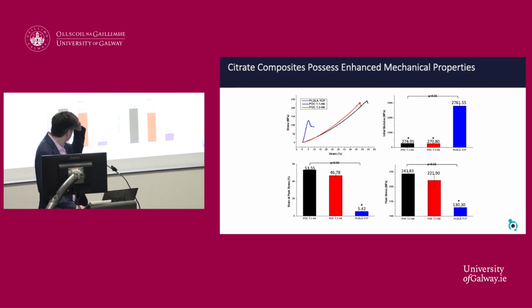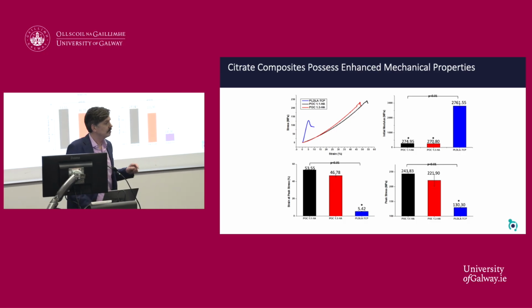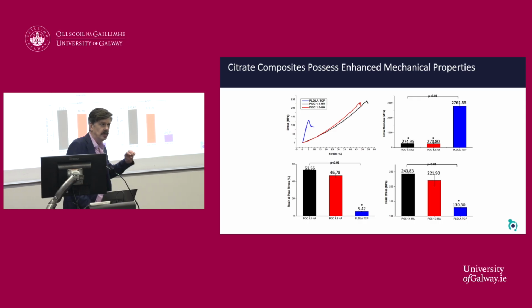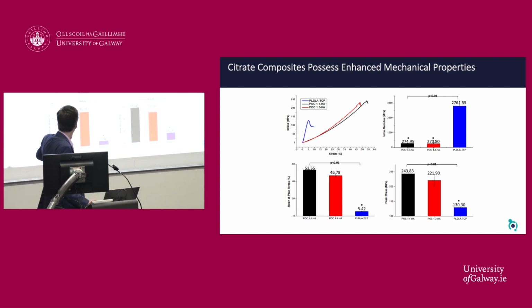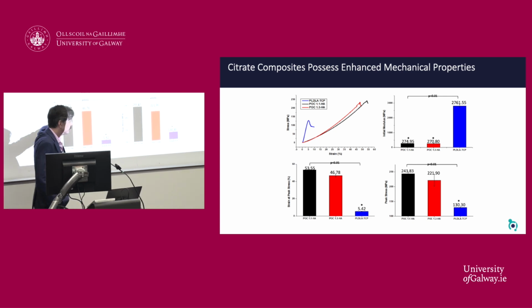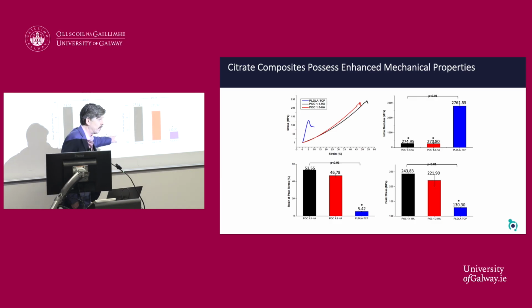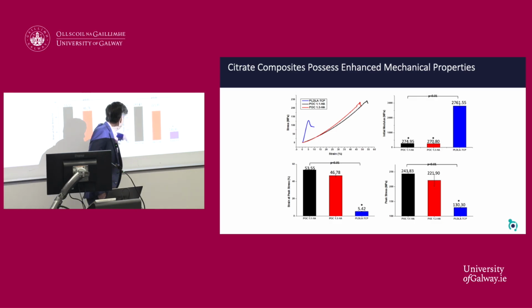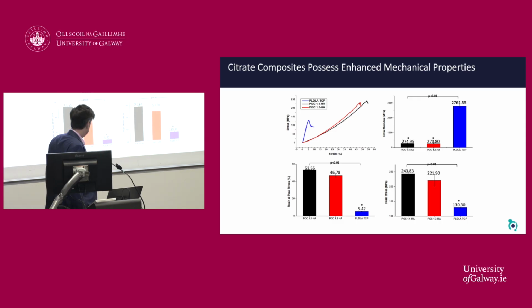We performed mechanical analysis. Mechanically speaking, our materials were far lower elastic modulus. They were far more robust mechanically. They were stronger and less brittle. So the competitors' industry gold standard are harder, but they're quite brittle. Our materials are slightly more elastic, more robust. They had a strain at peak stress of about 50% relative to 5%, so an order of magnitude greater than the gold standard, and they had a significant increase in their peak stress, about 220 megapascals relative to the gold standard.